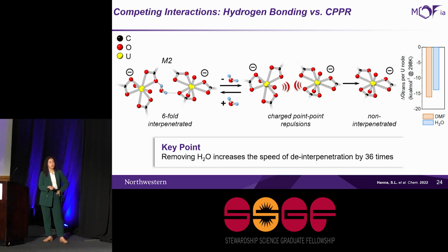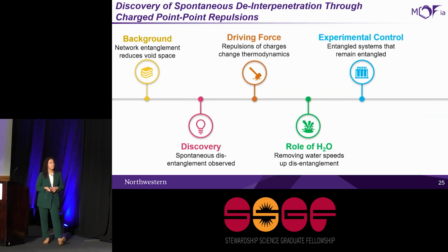I also did an experiment here to show that this could be possible. I removed water from my reaction conditions and was actually able to speed this up by 36 times and get de-interpenetration in 4 days instead of 5 months, just by showing that these competing interactions really do occur.